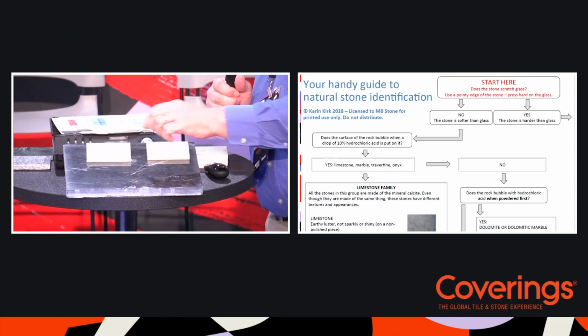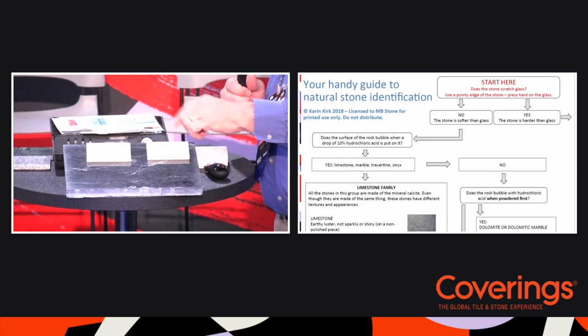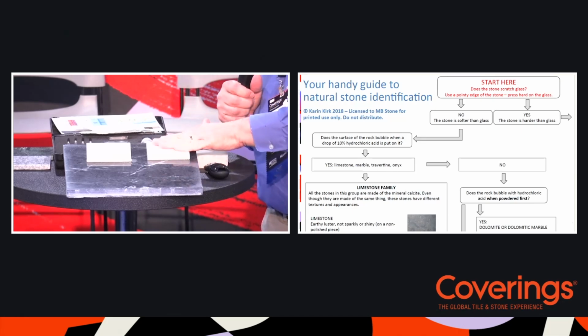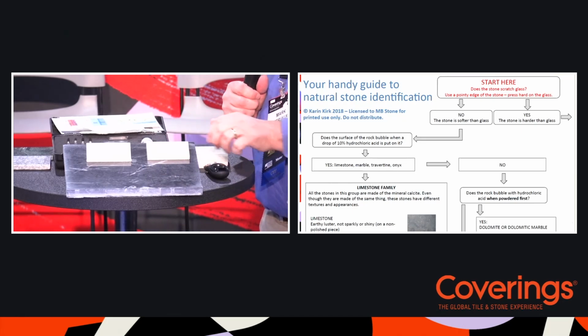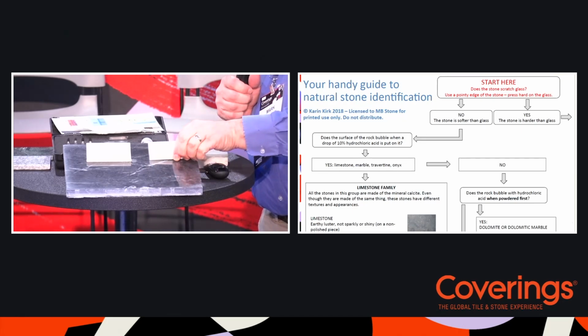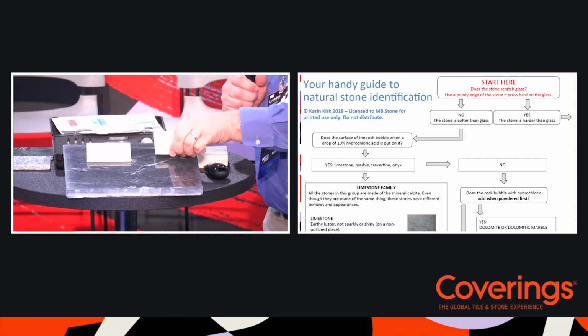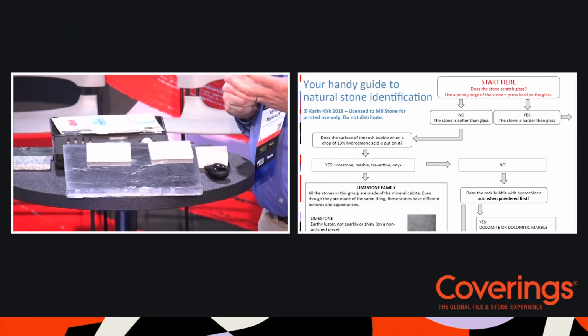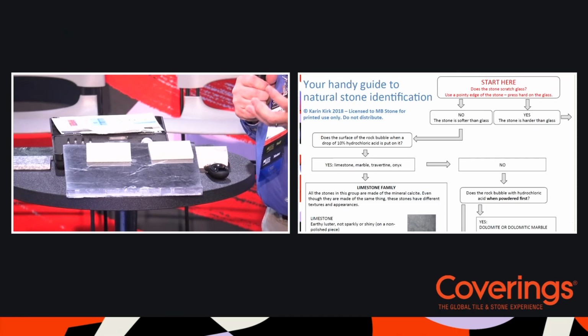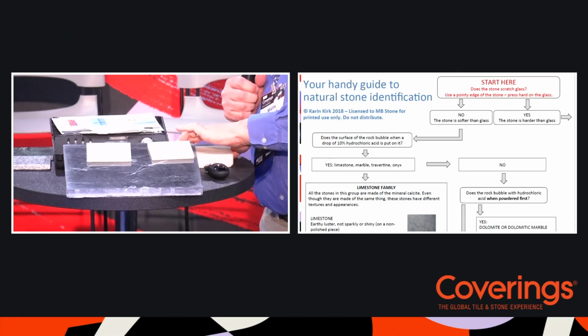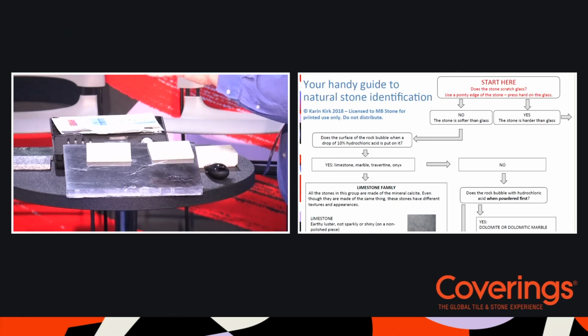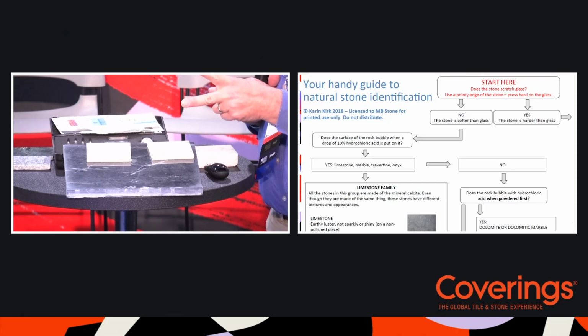We've got some materials we can test. I know we've used these before, and we can speed it up because I see some etch marks on here. The white materials don't show up on our camera very well, but these are also acid sensitive. Very generally speaking, the very light, whiter materials are generally going to be composed of that calcium carbonate mineral. So this kit is designed to do those 2 primary tests: the scratch test, and then an acid test. That kind of test gives you more of the detailed stuff.